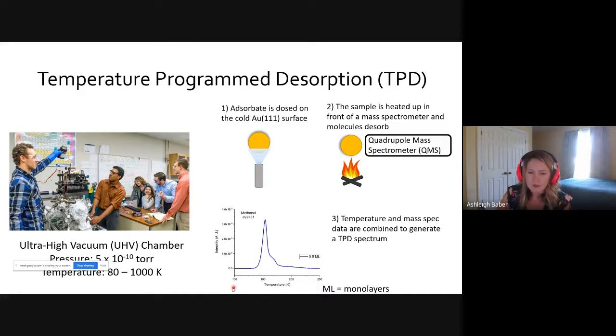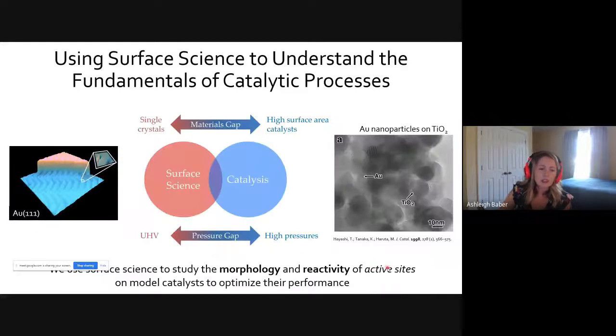If you haven't seen this before or recently, I'll just run you through this because this is mostly what I'll be showing today. So on the y-axis, you have the intensity of the desorption feature that's being monitored. In this case, methanol, we're looking at a mass-to-charge ratio of 31. And so you can see the desorption of methanol as a function of temperature. And so if we have molecules coming off of the surface at higher temperatures, that gives us information about how strongly the molecule is bound to the surface. And you can see we have a few other features that are present here, and I'll be talking about that as we go through this talk.